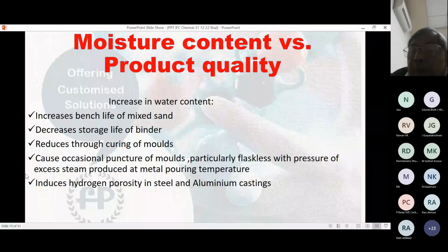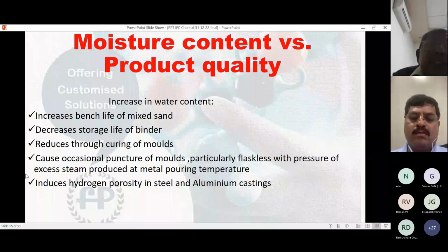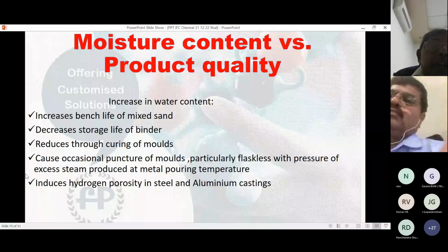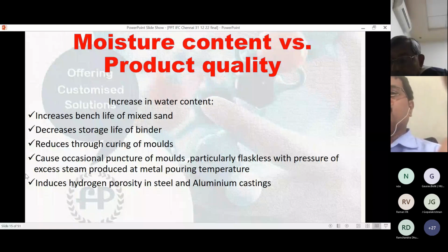Then comes the moisture content. Increase in moisture content increases bench life of mixed sand, but decreases storage life of binder because the phenolic component of your resin slowly advances, and when it advances to a particular stage, then viscosity increases. It reduces through curing of molds because water, as you know, remains and does not evaporate from the system, neither is it getting consumed in the system. In case of flaskless molds, it causes occasional puncture of molds because of formation of extra steam at the pouring temperature of metal, and it induces hydrogen porosity in steel and aluminum castings.